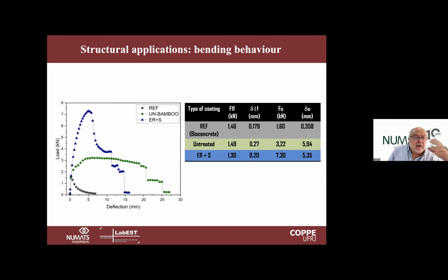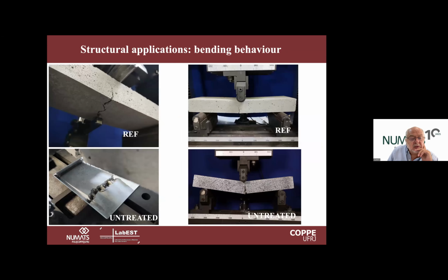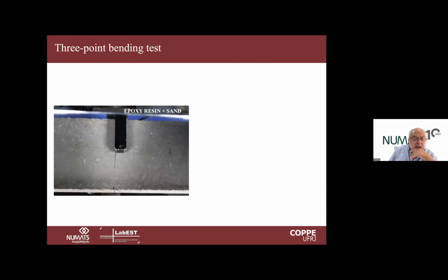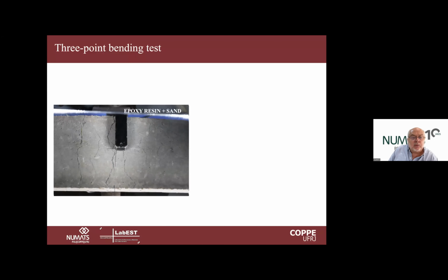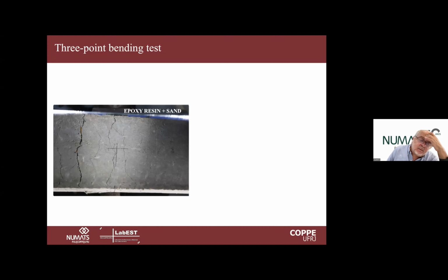Again, here we have a very nice response, which gives us optimism to design these materials for many possibilities of structural systems, building systems. And you see here the failure mode, when we do not have any, just the fibers in the bioconcrete, the bridging effect is quite reduced. We form only one crack. When we have untreated bamboo, we have some slip between the bamboo and the bioconcrete at a late stage of the bending process. But when we use the treated segments, you see here a multiple cracking formation with controlled cracking process. So this gives us really a very optimistic view of the use of this system of bamboo as reinforcement of bioconcrete.